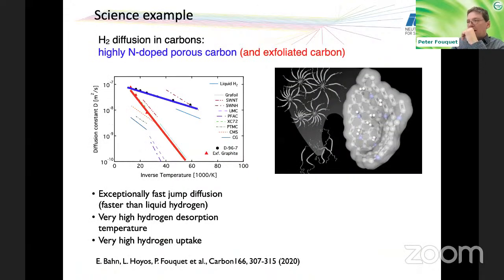Now I want to, after closing this, just show very briefly two other examples. One would be hydrogen diffusion in carbon materials, and that's a typical example of hydrogen storage materials that can be produced quite ecologically from existing carbons. And there we looked with a group from South America on a newly produced nitrogen-doped porous carbon. And in this study, we looked in particular at hydrogen motion as a function of temperature compared to normal exfoliated graphite carbon.